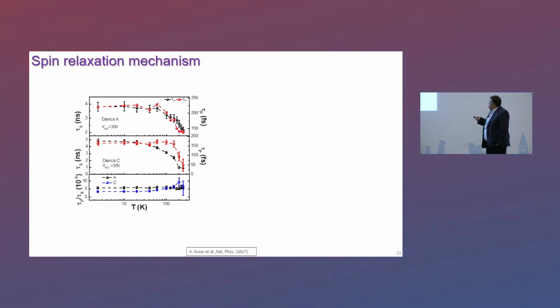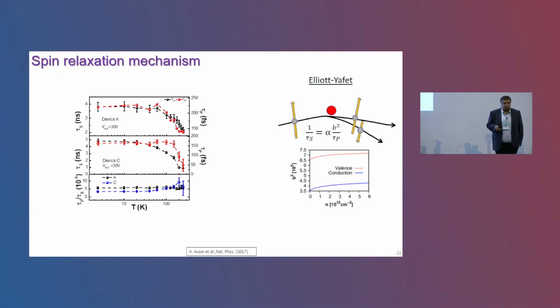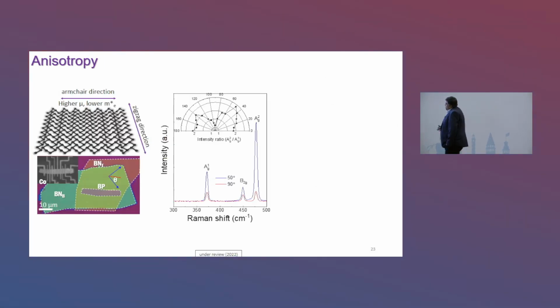And this is very much an indication of the Elliott-Yafet spin scattering mechanism, meaning that the spins are mostly relaxing during the momentum relaxation events. We experimentally determined the spin mixing probability, a parameter which you can obtain by comparing the spin and momentum relaxation times, and the values are almost exactly matching what our theoreticians at Regensburg have determined. This means that in this material, which we are preparing in the glove box environment, we are almost approaching the intrinsic spintronics properties of the material. Okay, so this was the basic characterization of the spin transport in this material.